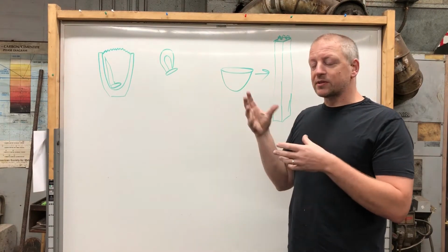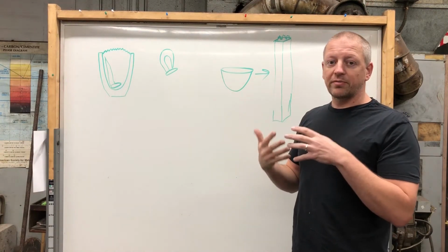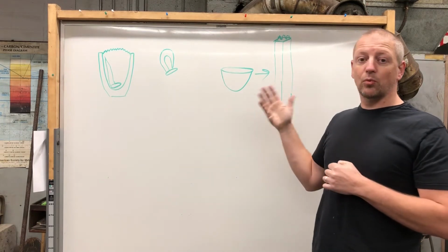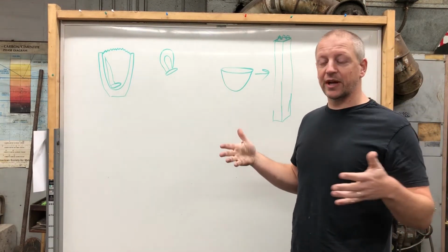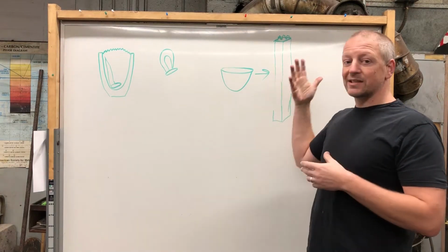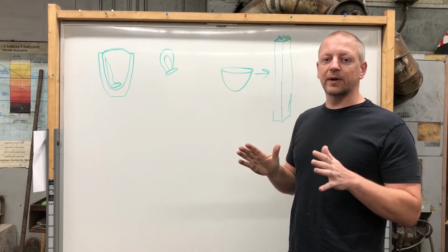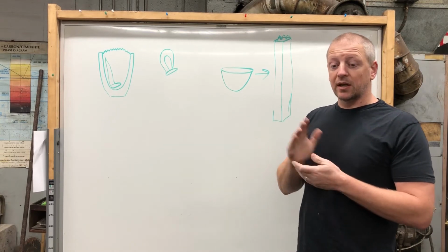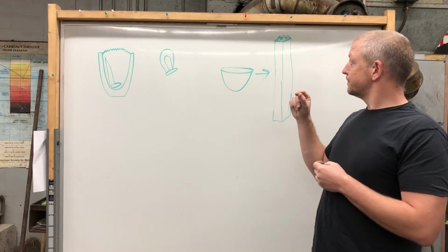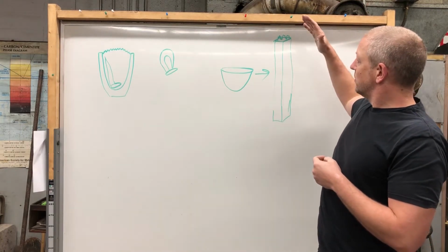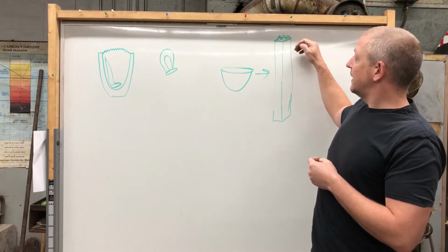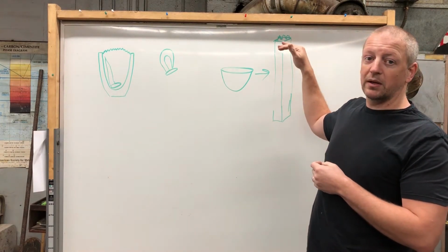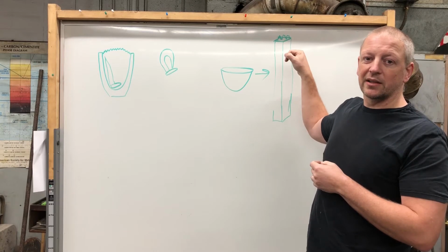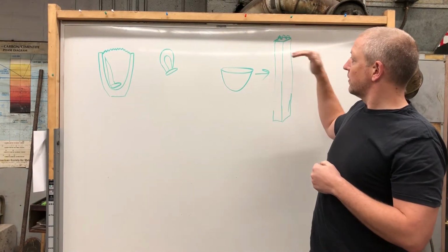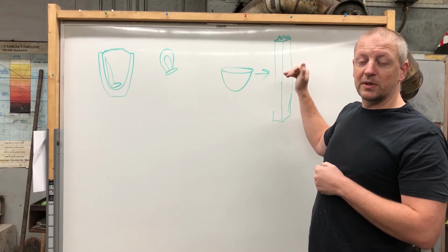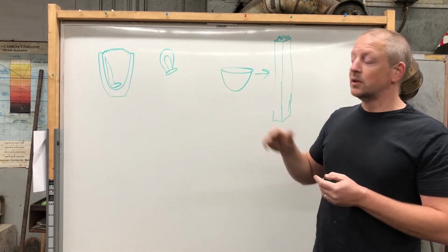But what I've found over time is that because the dendrites start off oriented in every direction, it really doesn't matter which way you forge it, which direction you forge it out. You're going to get essentially the same pattern. I've tried all different ways. And actually, on this ingot, I do a little demonstration of that because after forging out to this stage, I trimmed off the crunchy butt, realized that I still had some odd cracking that extended further down. So I trimmed off a series of pieces until I got down to solid material.